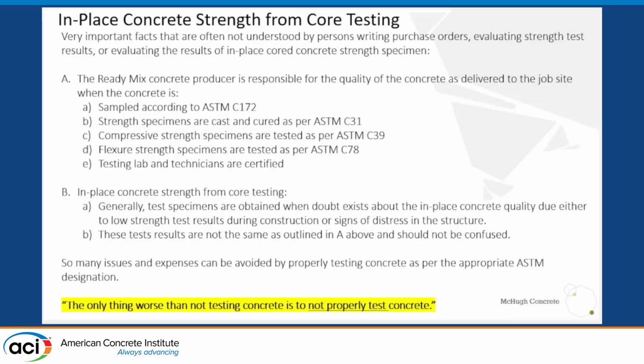Very important facts that are often not understood by persons writing purchase orders, evaluating strength tests, or evaluating results of in-place core concrete strength specimens is you've got category A and B. So A, the ready mix producer is responsible for the quality of the concrete that's delivered to the job site when the concrete is sampled according to ASTM C172. Strength specimens are cast and cured as per ASTM C31. Compressive strength specimens are tested per ASTM C39. Flexural strength specimens are tested per C78, and the testing lab and the technicians are all certified. So there's a whole bunch of ASTMs there, and qualified people following strict procedures.